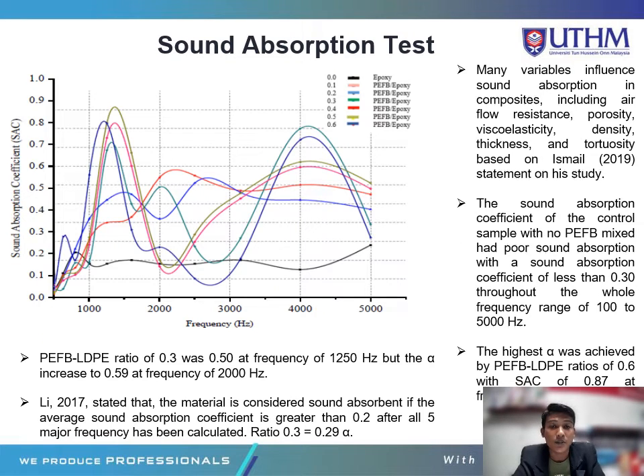For the sound absorption test, many variables influence the sound absorption in composites, including air flow resistance, porosity, viscoelasticity, density, thickness, and tortuosity, based on Ismail's study 2019. The control sample with no PEFB had poor sound absorption, with a sound absorption coefficient, SAC, of less than 0.3 throughout the whole frequency range of 100 to 5000 Hz.